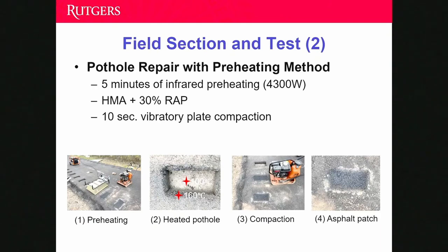And then we did a compaction using a vibratory plate compactor for 10 seconds. Initially, we also tried using a steel tamper to do the compaction based on the current standard from NJDOT. But it turns out that we cannot get intact field cores because of the torsion from the drilling machine. We found that the field cores were damaged after drilling. So we think maybe the steel tamper cannot ensure good compaction quality. So in that case, we cannot get field cores for further mechanical testing. And then we decided to use the vibratory plate compaction.